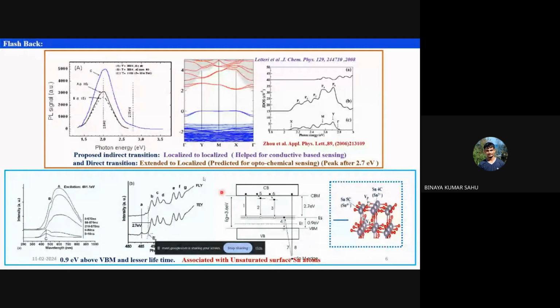So in principle, if the band gap is around 3.6 electron volt, I should get a peak around 3.6 electron volt. And this is the typical spectra of tin oxide. But you can clearly see there is no peak, no humps or peaks around 3.6. Why so? Because this transition is not allowed for tin oxide because of the dipole forbidden rule. Those who have studied perturbation theory in quantum mechanics can go and check. There's something called the dipole forbidden rule, and because of that, for tin oxide, this transition is not allowed.